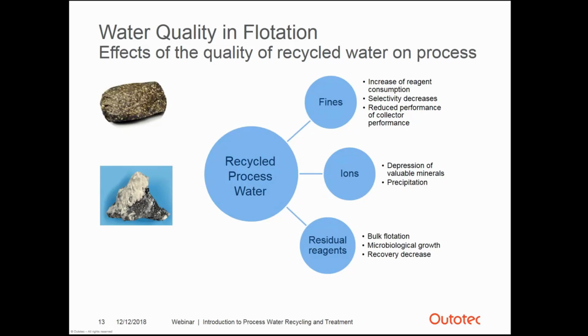Then the last group, residual reagents. Presence of residual reagents in the process water may cause bulk flotation, which compromises selectivity. And then, for example, residuals of CMC reagent, carboxymethyl cellulose, in process water can cause microbiological growth and also unwanted depression and recovery decrease.